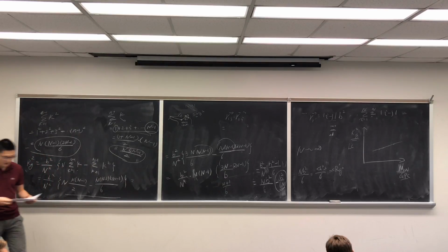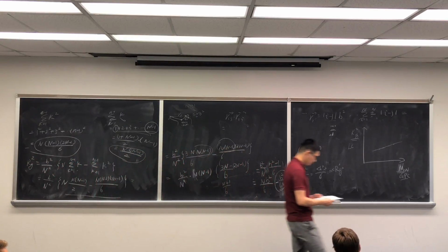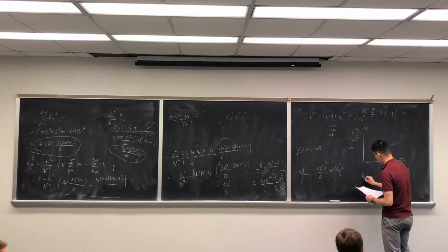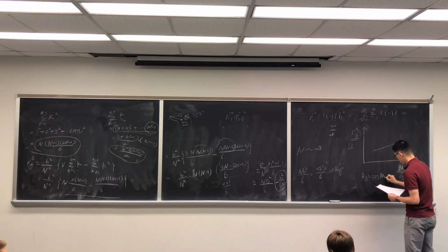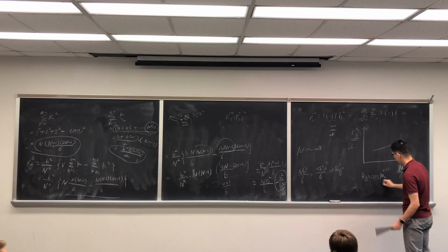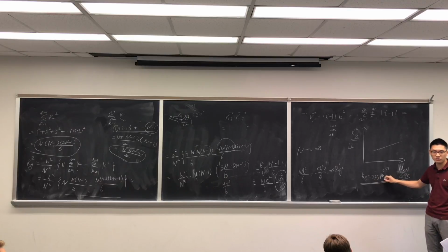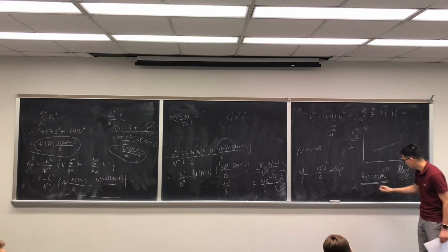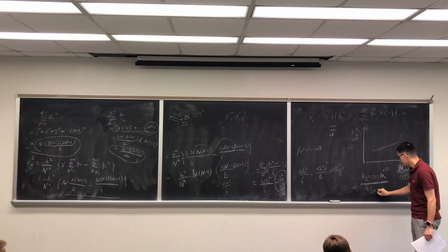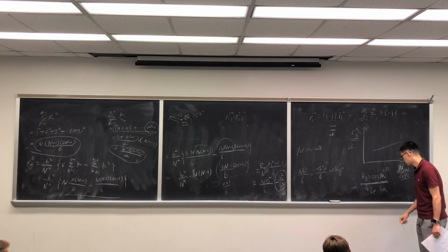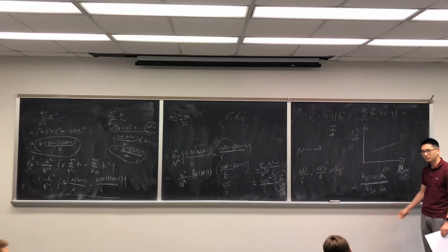For example, I won't go in too deep, but let's say you get Rg can be plotted as 0.25 times molecular weight to the power of 0.51. I mean, this is possible, right? You can plot them and you can get what the slope is and what these values are. So if you can get this type of relationship, you can directly get the persistence length, characteristic ratio, and you can know a lot about chain conformation for your sample.